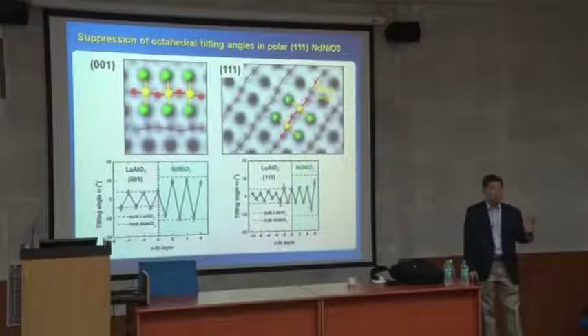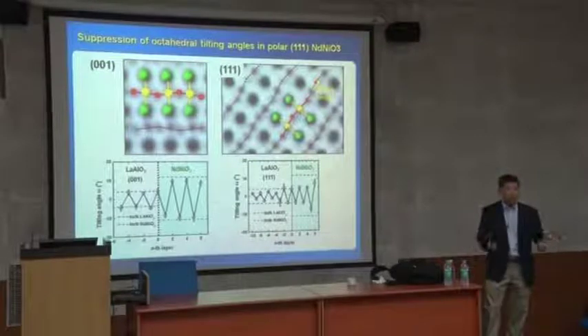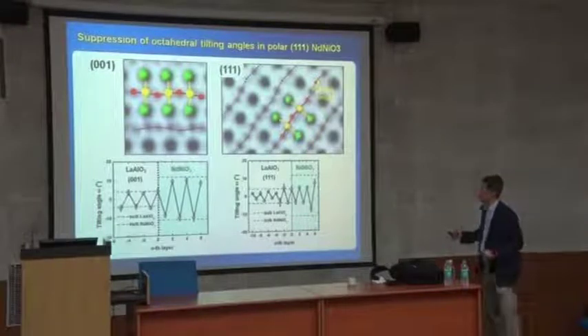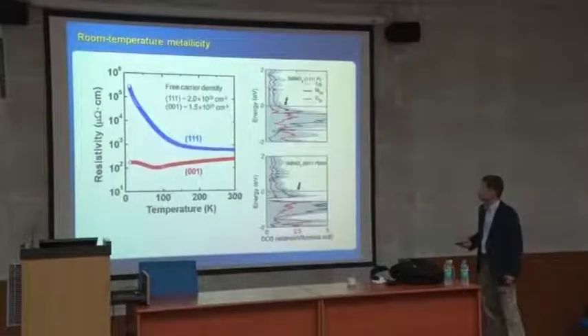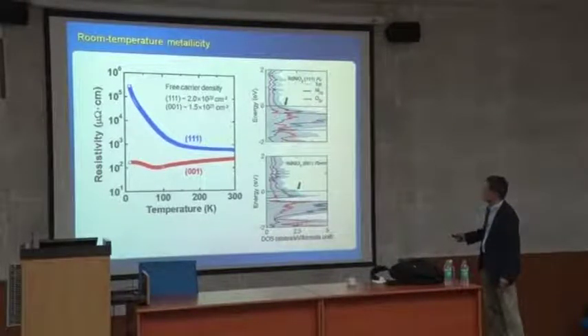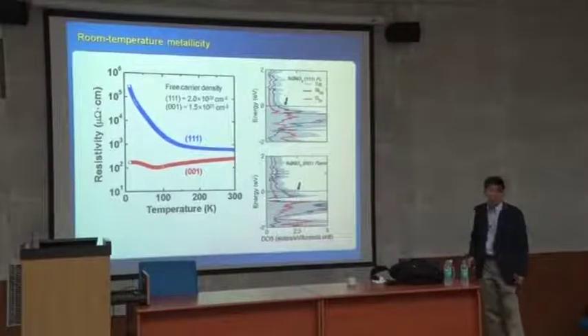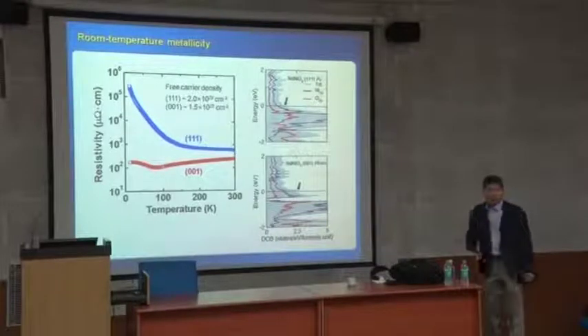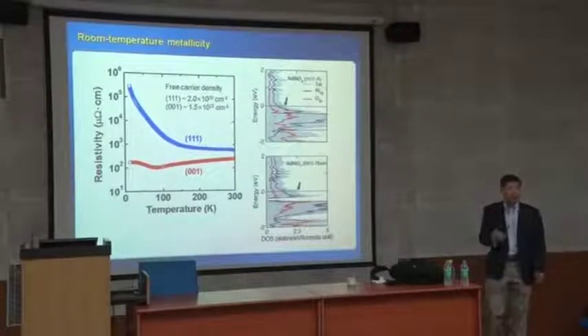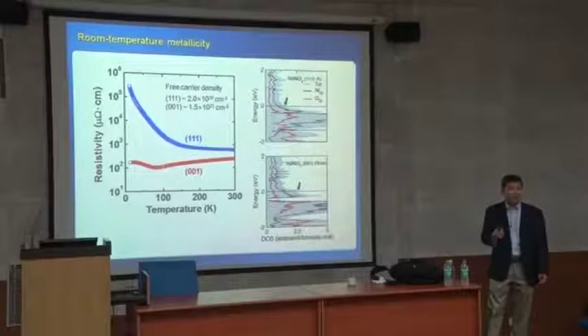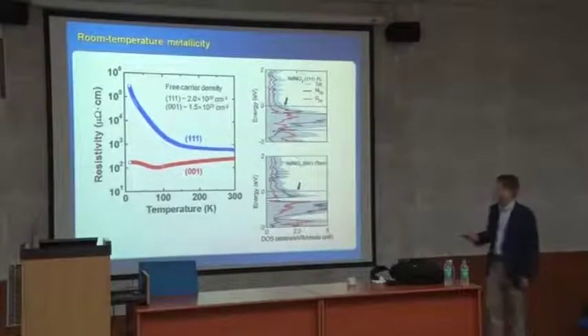And then it's a very key piece of information because you have macroscopic non-centrosymmetry, but really non-centrosymmetric, and that is confirmed by this method. And also we have to measure these band structures here, and you have the density of states around here, the Fermi level, and in both cases the metal is showing metallic behavior. So that is the one way you can actually make polar metals from non-polar by structural tuning, by heteroepitaxy. Okay, that's what we show.